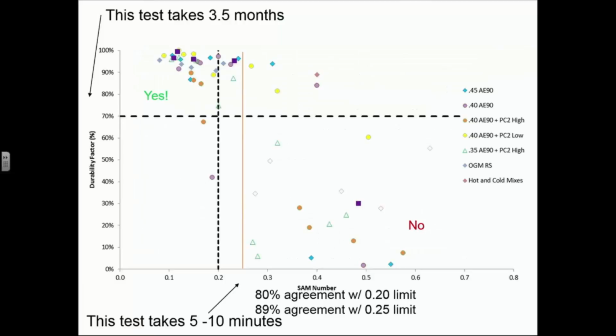Okay, now let's move into freeze-thaw durability. For freeze-thaw durability, we've got the SAM number down here on the x-axis. We've got the durability factor on the y-axis. Remember, this is the test, SAM number. This is the test. It takes 5 to 10 minutes that you get into the fresh concrete. Durability factor, this is the one from the ASTM C666 test. This test takes 3.5 months to run. That's a long time. But again, if we use the 0.20 limit right here, this is the yes quadrant, this is the no quadrant, there's an 80% agreement.